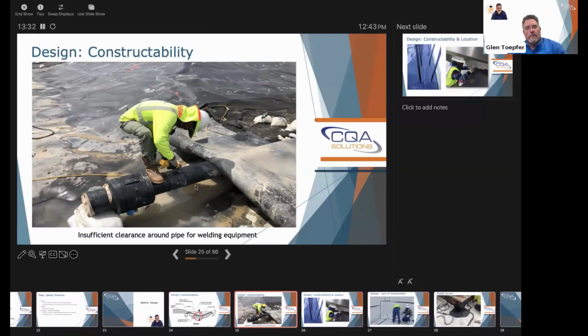And this photo really shows you the insufficient clearance around the pipe to get welding equipment in. Even whatever he's doing up here on the top, if he's going to try and do that underneath, I've seen people just fit it in by hand and try to roll it with a roller because they can't get the extruder in there. But we need to design things better. We're setting ourselves up for failure for poor weld quality because you're not getting the pressure, and in some cases the heat.